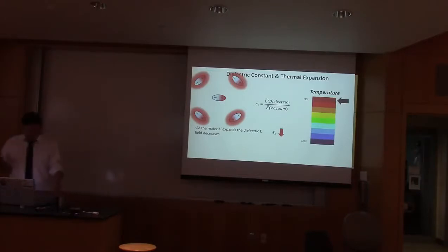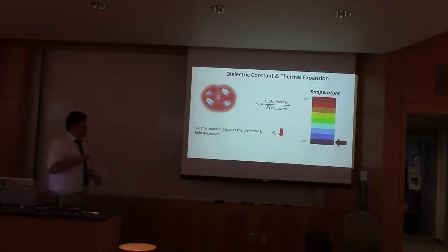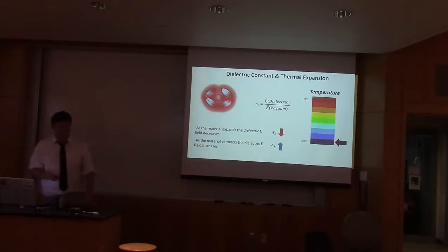As we increase the temperature, these dipoles get further and further away from each other, and therefore they are less effective in interacting with this molecule, with this dipole. This idea means that because we have fewer dipoles in a given volume, or the dipole density, if you will, of that given volume has decreased, therefore we'd expect the dielectric electric field to also decrease. So with increasing temperature, we note that the dielectric constant goes down, and then we can imagine if we went in the reverse and cooled it down quite a bit, the dielectric constant, because of these close interactions with the other molecules next to it, increases as the dipole density increases itself.